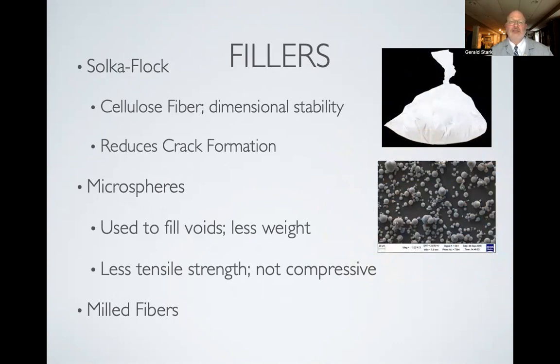And then also using fillers, Solka-Flock, which is really a refined cellulose flour. It's a cellulose fiber, gives it some dimensional stability, but very little strength. Microspheres also provide a bit of strength to fill these voids, but it gives no strength at all. It's used to fill the voids. It's not for compressive strength, maybe some tensile resistance. But again, both of these materials can also create small slivers and are not biodegradable. So you have to be very, very careful with all of these types of devices.